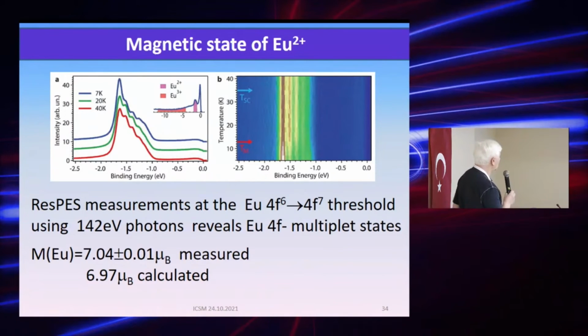More information can be obtained from resonance photoelectron spectroscopy measurements at high energy of photons, which here the picture shows the response in intensity at about 142 electron volts, which is due to the resonant transition in europium 4f6 to 4f7 threshold. And it shows the multiplet of states, and the spectral weight transfers from the side levels to the ground state as we cool down the temperature.